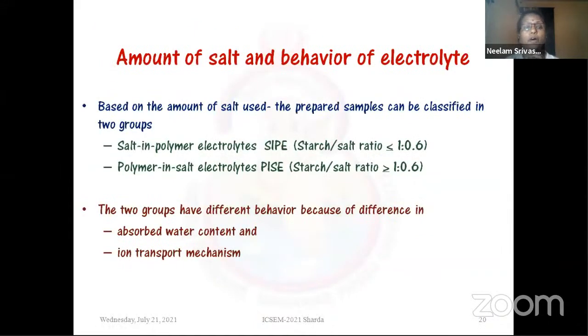So a very nice protocol has been developed by us, and we have found that if we vary the salt concentration from the concentration which is mentioned here, meaning how much gram of starch and how much gram of salt we are using. So till the starch is 1 and salt amount is less than 0.6, till then we are in the SIPE system, that means salt in polymer electrolyte system. But the moment we increased the amount of salt greater than 0.6, then it has transferred into the PISE system. And both the groups have their own importance, but in today's talk I am limiting myself to the PISE system.